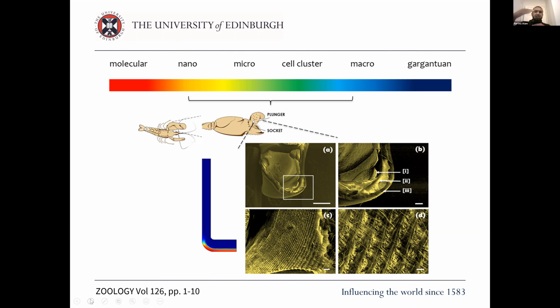And then in between those, you've got this. If you look at images C and D in that slide, you've got this layered Christmas tree porous structure that is actually made out of chitin. So basically, what's happening here is that the heat, and we modeled this, and you can check the paper, is really interesting. The model is that the heat can go through the first layer, that's the hard layer, right? That's probably good for pressure. But then the heat does not go through this middle layer, which is this laminated Christmas tree-like porous chitinous structure.